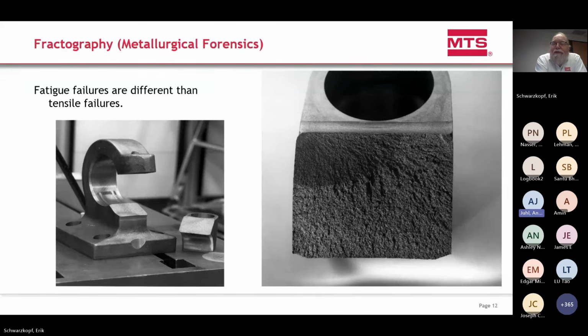Fatigue fracture surfaces are very different from tensile fractures. This is an example of a failure here at MTS that started at the surface, and you get a characteristic thumbnail — a fracture that radiates out from the initiation point.